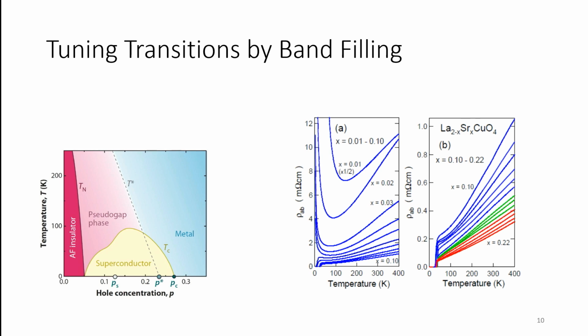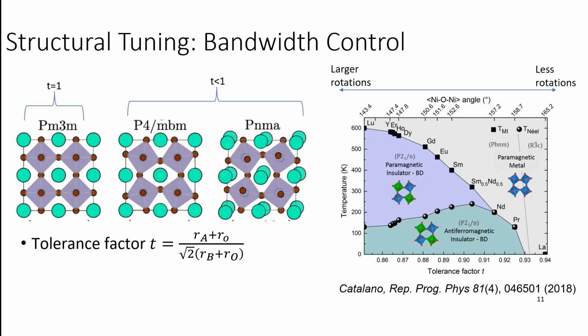As you change the hole concentration, you go from this anti-ferromagnetic insulating state. Anti-ferromagnetic means spins point in opposite directions. The system is a really bad conductor of current. And then at some really precise range of doping levels, you end up in this superconducting dome phase. So in this case, you are changing the amount of holes in the system, and you're using this as a way to tune what properties emerge in the system.